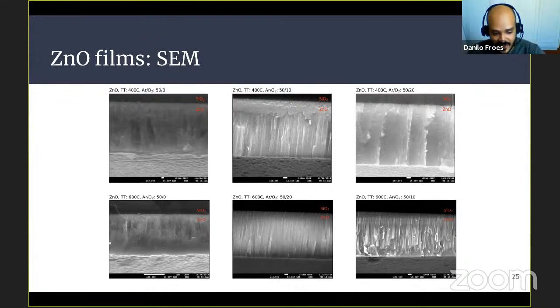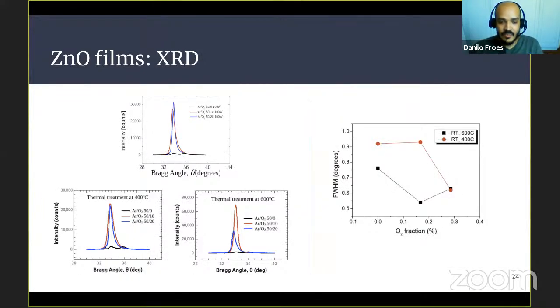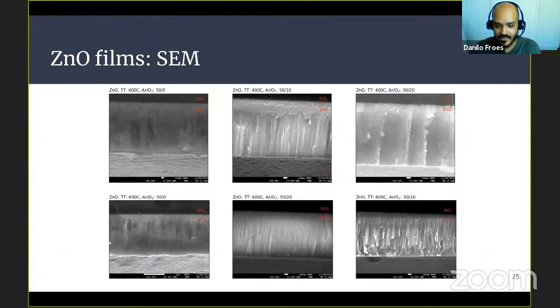The first thing I think is important to mention is that we wanted to do a fast deposition of the zinc oxide material in order to be piezoelectric. So we were not very careful with all the details of the deposition. I believe that was an error we made. We should have come back and measured the stoichiometry and done other types of measurements in order to verify the properties of the zinc oxide. But we didn't measure the stoichiometry. We were just comparing with how it was done in the literature and repeating it, doing some checks with the X-ray diffraction and the cross section in the electron microscopy. And after doing that, we went straight to putting on the interdigital transducer.